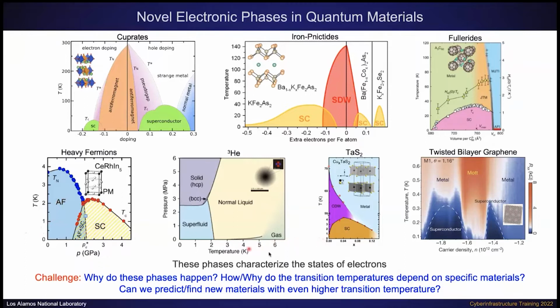And this then carries over to other ones. In helium, we have a superfluid phase instead of superconductivity. We have layered 2D materials that give way to charge density waves, so periodic distortion of the lattice due to charge, superconductivity, some metal. And then the most recent surprising discovery, made in, I believe, 2018: if you take 2 layers of graphene, so you flake off some graphene from graphite, like from your pencil, and then you twist them about 1.16 degrees away from one another to create this moiré pattern, you arrive at a phase diagram that is very similar to the cuprates.